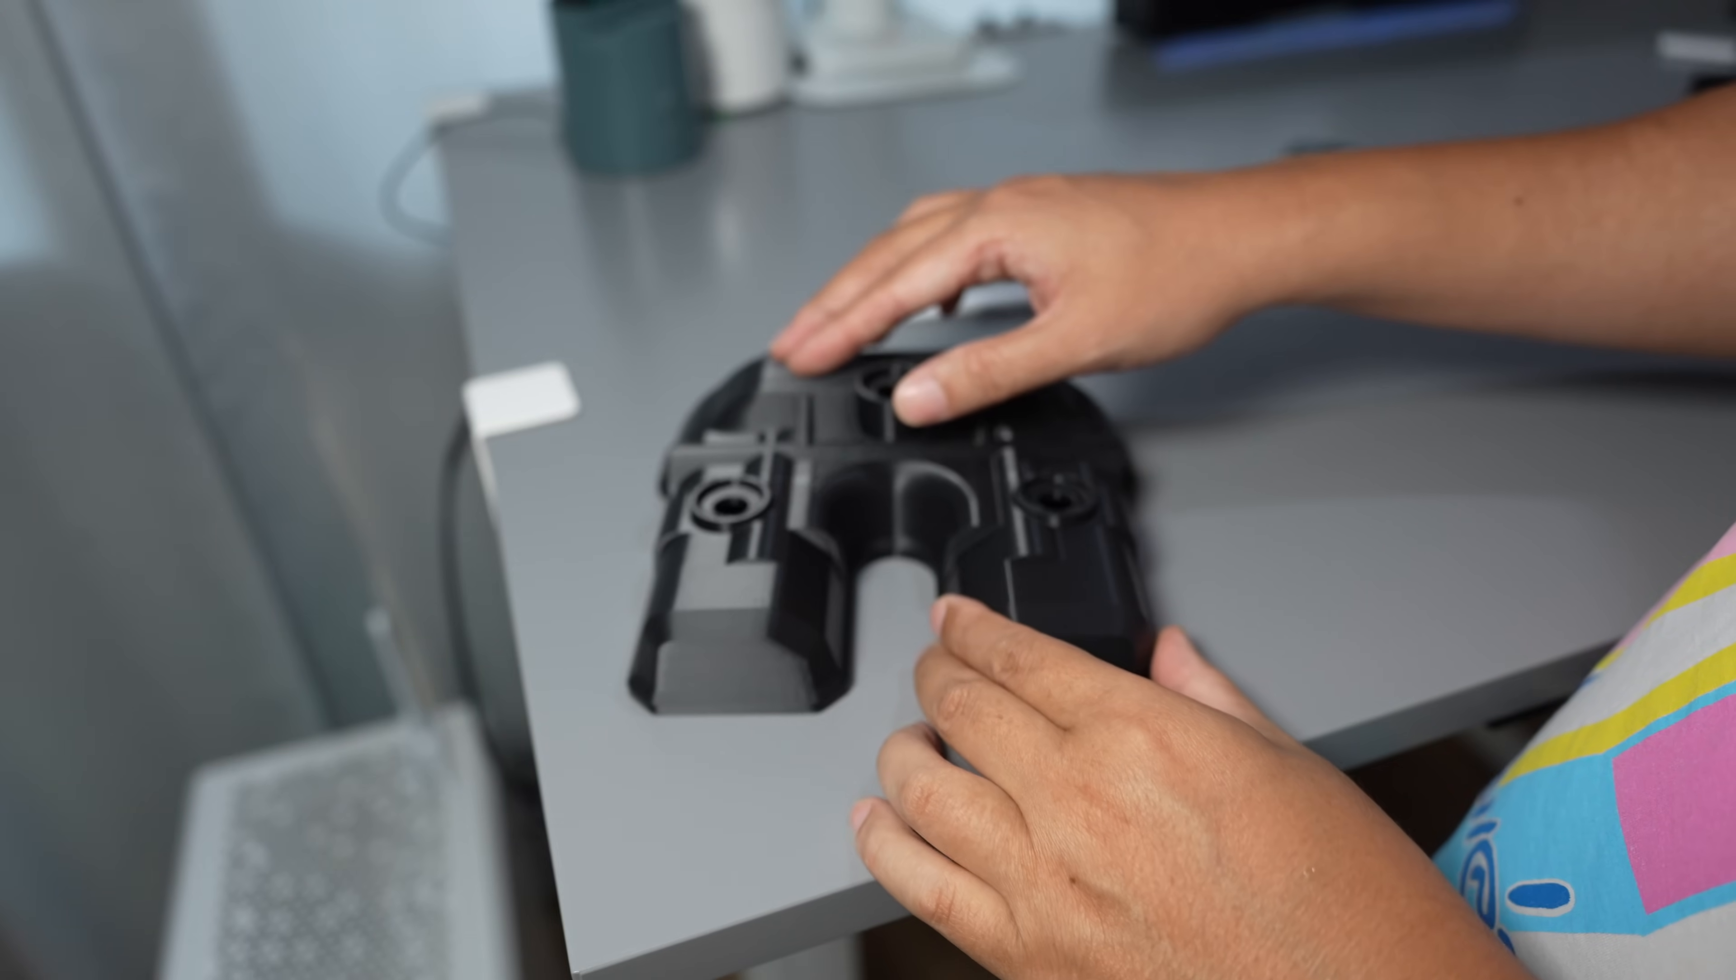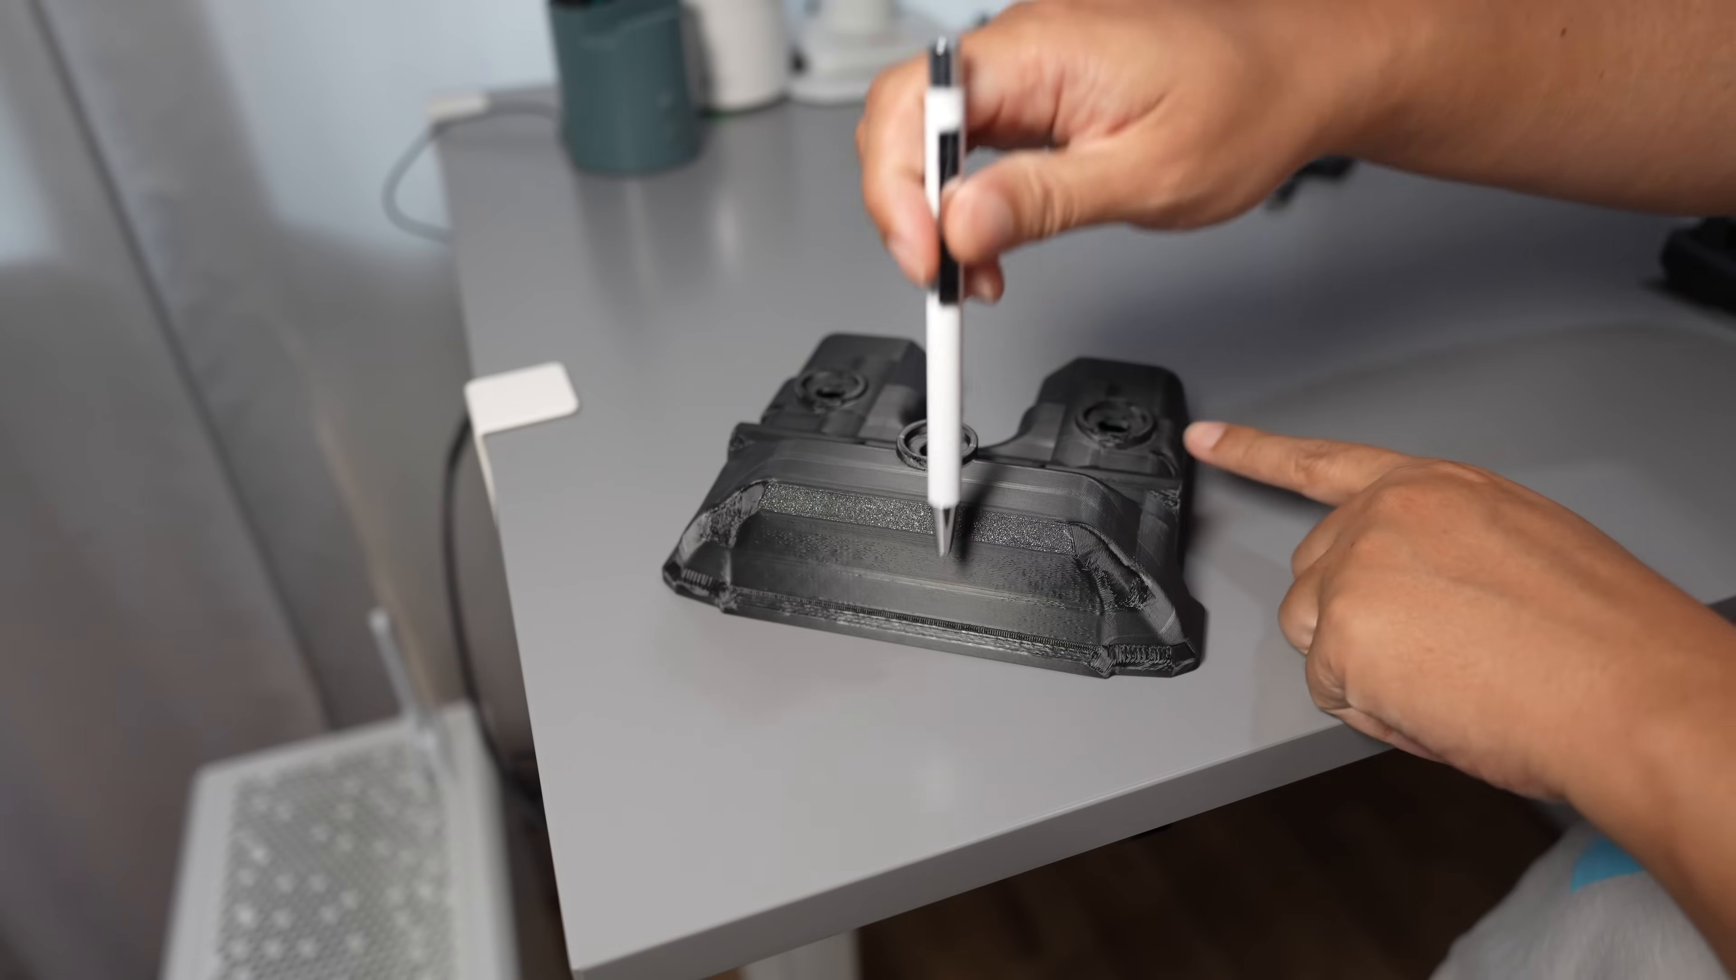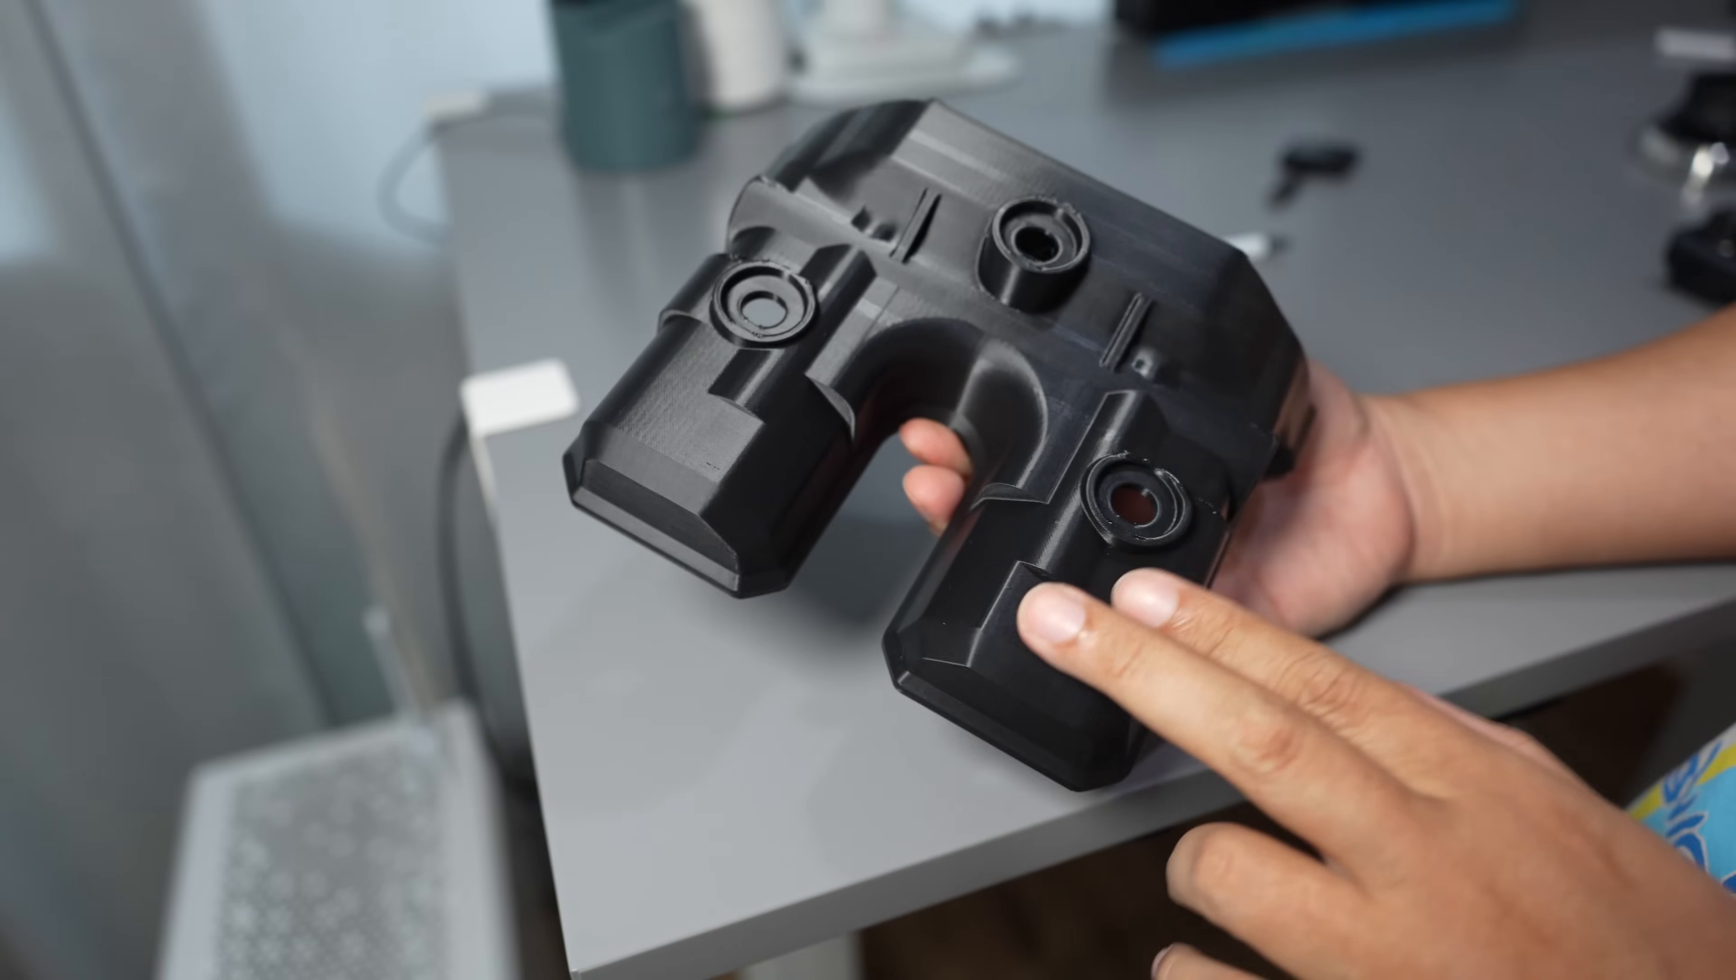When I put this model into a simulation and apply a nylon 6 material to this valve cover, when the force is applied over the bolt, this edge here will start to lift up for 7 millimeters and the back panel here will bulge when it's printed with nylon. Even with carbon fiber, this part will deform too much and the oil seal will lift up from the engine valve and the oil will leak.